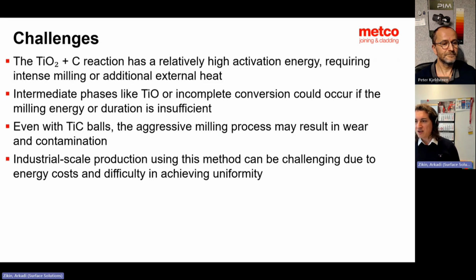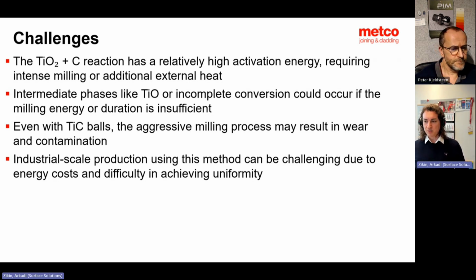The challenge we faced was that when titanium dioxide reacts with carbon, it requires a high energy level. Yes, absolutely. And intense milling. To form this cycle and realize that you can get all titanium dioxide transferred to titanium carbide was not easy. Of course, you can get some contaminations, because wear happens not only on balls, it can happen also on the housing of the rotation tumbler. So you still can get some particles which you would not wish to have there because of aggressive milling.